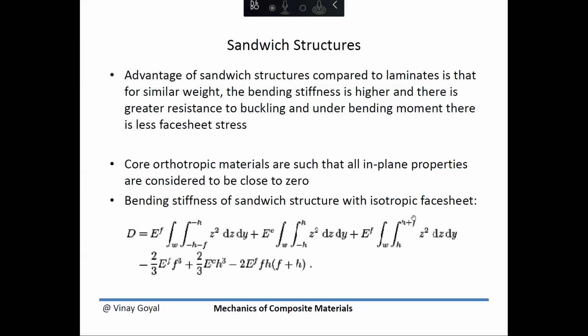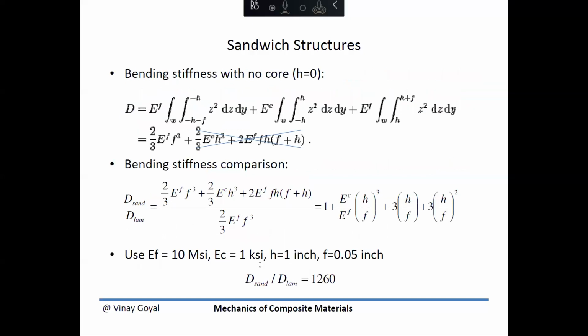And so here, what I have now is, I have found this to be the expression for the bending stiffness after I work through this. And so if the bending stiffness with no core, so there's no core, H is zero, all this goes away. So the bending stiffness is simply 2/3 E_f f cubed. Okay, so that's very clear that that's what you will get.